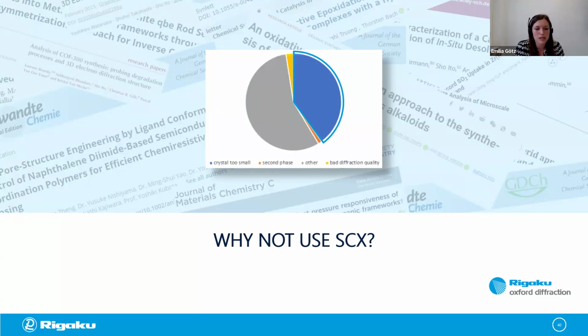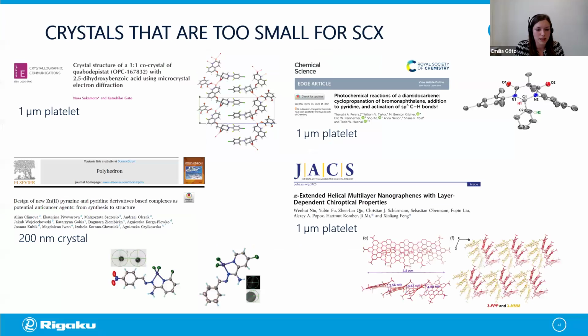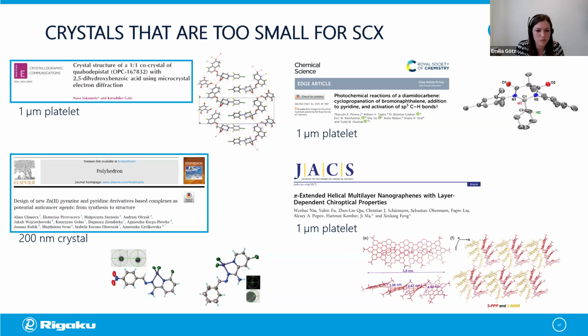But there were also some other reasons named, like having a second phase included or a bad diffraction quality during X-ray measurements. So let's look at some publications with crystals that were too small. In this paper by Sakamoto and Gacho, a structure of a co-crystal was solved where the crystals were 1 micron in size, but they were very thin platelets only. And in this paper by Klimova et al., potential anti-cancer agents were solved with the Synergy-ED, with crystals being in the size range of only 200 nanometers.